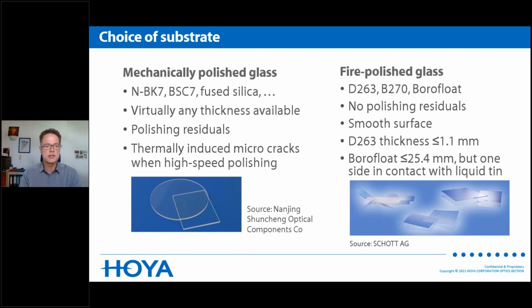But you might see that it's not always possible to remove all the polishing residuals, which can create a problem for the growth of the thin film layers on the substrates. And of course, companies try to optimize production time, so they tend to use high-speed polishing, which might induce micro cracks in the surface, which again is not very good for the growth of the thin film layers.